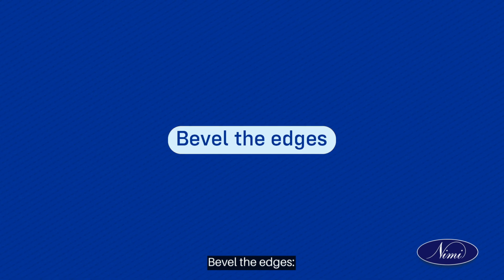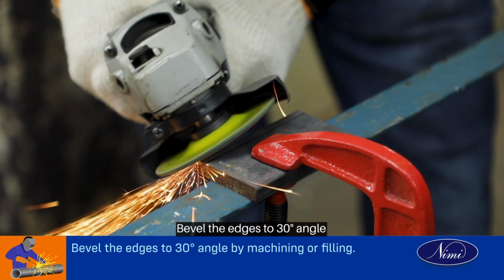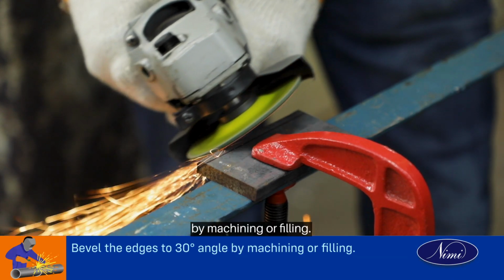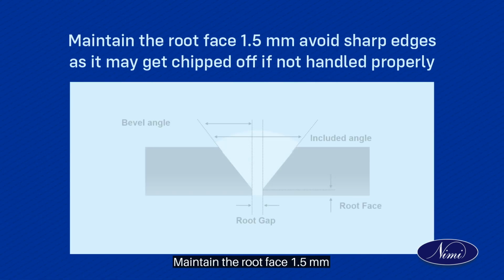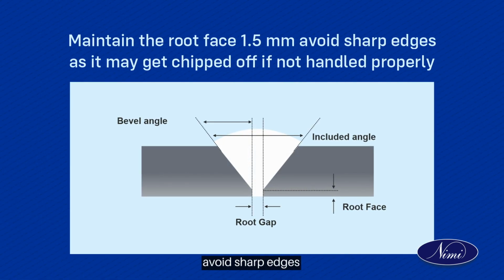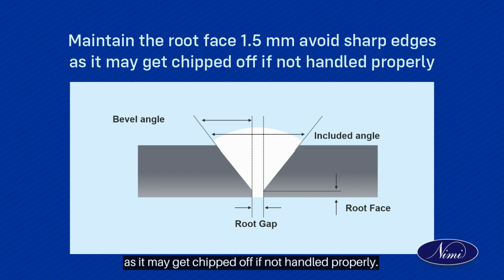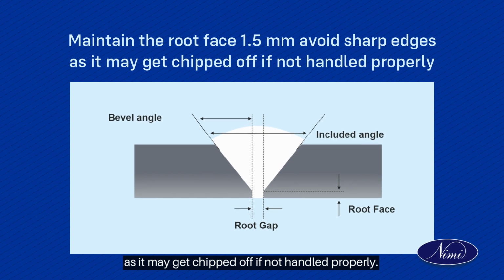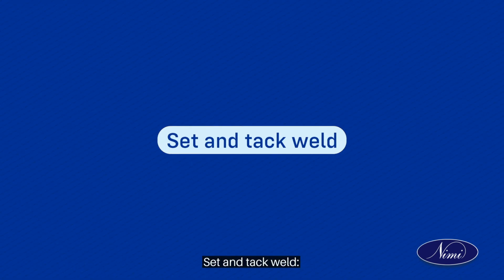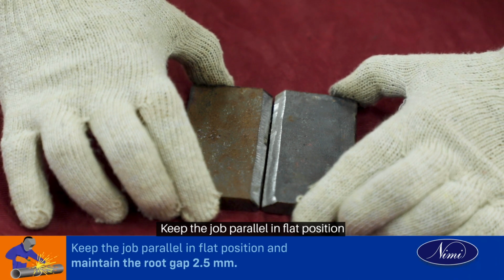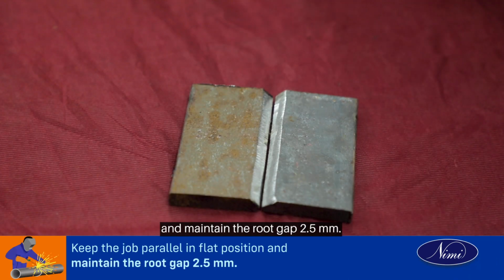Bevel the edges. Bevel the edges to 30 degrees angle by machining or filing. Maintain the root face 1.5 mm. Avoid sharp edges as it may get chipped off if not handled properly. Set and tack weld. Keep the job parallel in flat position and maintain the root gap 2.5 mm.